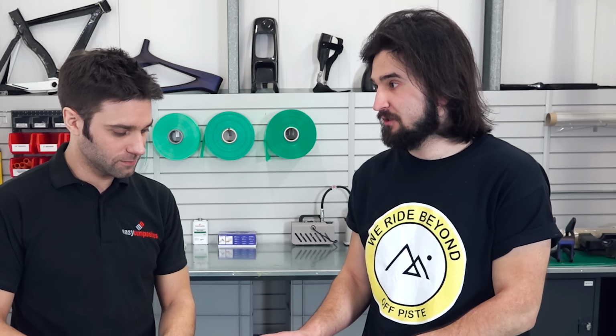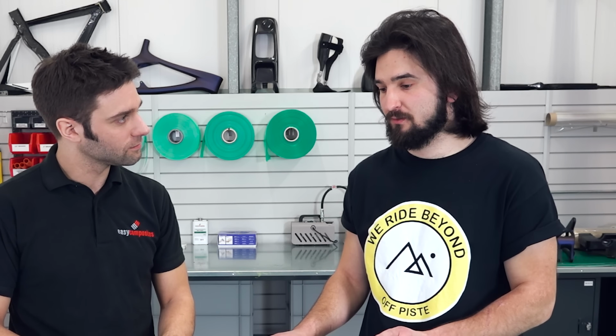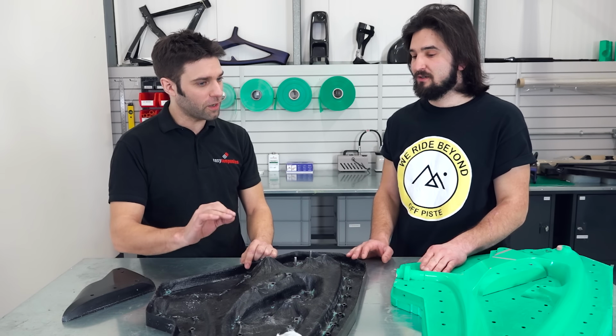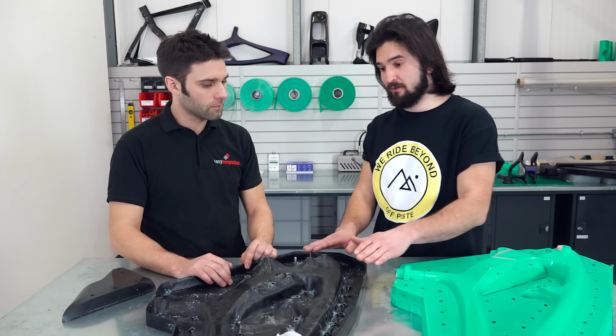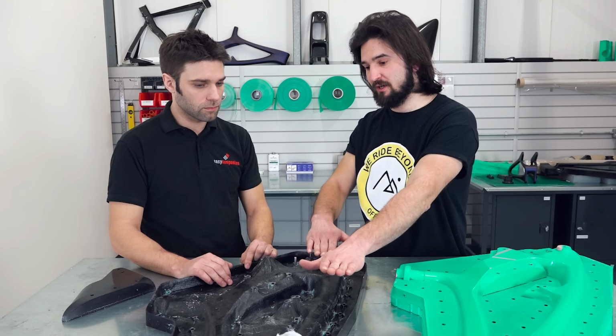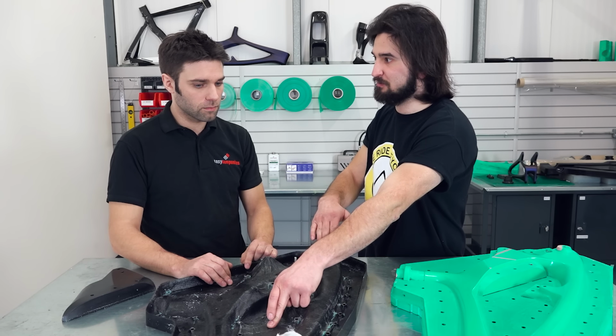Just to add on for the post-cure, we had both halves together bolted up because the flatness of the board is, even after it's machined, the board always has a little bow. Okay, so it's not perfectly flat. It's not perfectly flat. So in our case, the molds were, the edges were warped up, and the center was a bit lower.